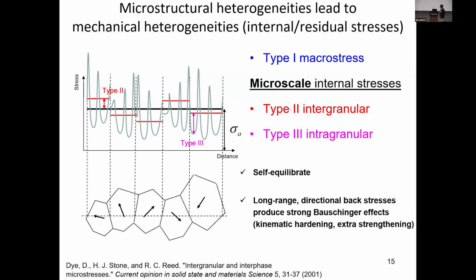While those micron-sized chemical and dislocation cell structures produce very strong stress fluctuations within the cells and across the cells. People have classified those stress fluctuations in terms of the characteristic length scales. At the sample length scale, this is the so-called type 1 internal stress or macrostress. That's not the focus of our research. We mainly focus on the type 2 intergranular and the type 3 intragranular internal stresses, as schematically illustrated here.